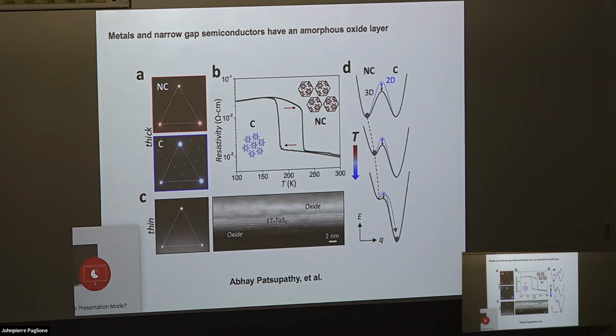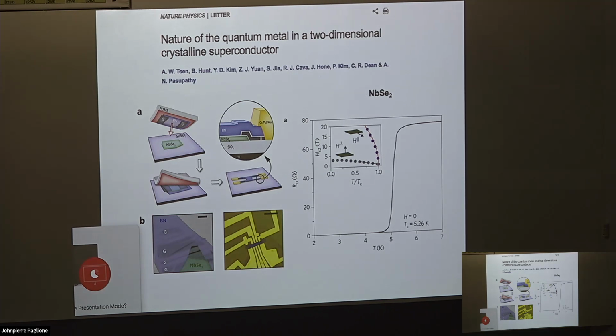One of the things about metals and narrow gap semiconductors is that they tend to form an amorphous oxide layer when they're exposed to air. So a lot of these are hard to work with in terms of single layer materials. Something you always have to watch out for. A lot of the developments in recent years has been learning how to handle these issues, how to prepare devices without exposing the layers to the atmosphere. Here's an example of how they made a niobium diselenide superconducting flake. You basically protect it with some boron nitride. They had this polymer stamp here, boron nitride. They did all this in the glove box, and they made some leads and everything without letting it see air. So it gets more complicated, but it's still doable. All these details have been worked out now.